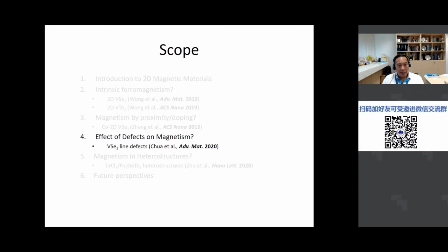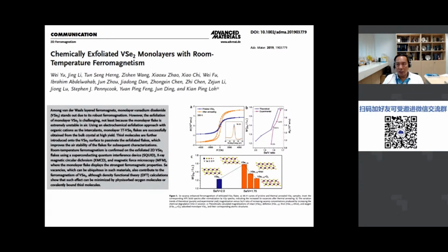I come to my third question now, and this question tries to answer a possible reason for observation of magnetism in those intrinsically non-magnetic 2D materials. What is the effect of defects on magnetism? So this paper, which was published last year, is done by my colleague, Kian Ping Loh, in the chemistry department. And this time, being a chemist, they produced the VSe2 by chemical exfoliation, unlike our method by MBE. But of course, a chemical exfoliation method does raise the concern about whether you could introduce impurities in your subsequent measurements. So their magnetic measurements show evidence of magnetism. You can see a little bit of hysteresis loop in what they call pristine vanadium Se2.